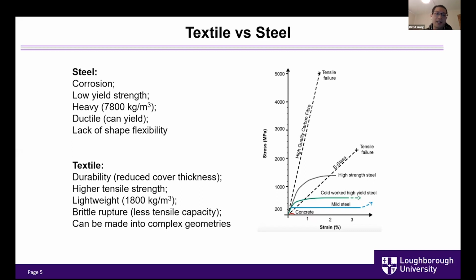Let's go to the textile. Textile is made of carbon or glass or basalt. There are different kinds of fibers we can use. All kinds of textiles are very durable, which means that we can try to reduce the cover thickness. This is especially competitive when we are trying to reinforce thin-shelled concrete elements. It has a very high tensile strength. In our study, we are going to use glass fiber. We can see from this figure that the E-glass fibers have a tensile strength of more than 2000 megapascal, which is much higher than the steel. And also it is very lightweight. It is 1/3 to 1/4 the weight of the steel.